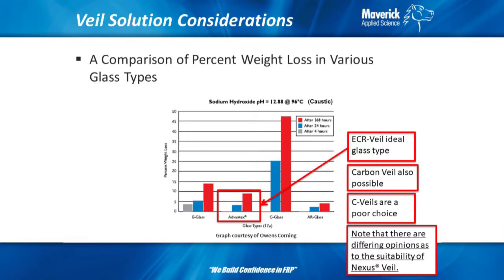In this case, for the caustic, this chart would tell you that the Advantex ECR glass, ECR veil, is a better glass type, and you can see the C glass is way up here, at least for pH 12.9 at almost 100 C. The C glass just gets completely eaten up in this case. Carbon veils are also possible for caustic. Like I said, C veils are a poor choice. Mike, go ahead.